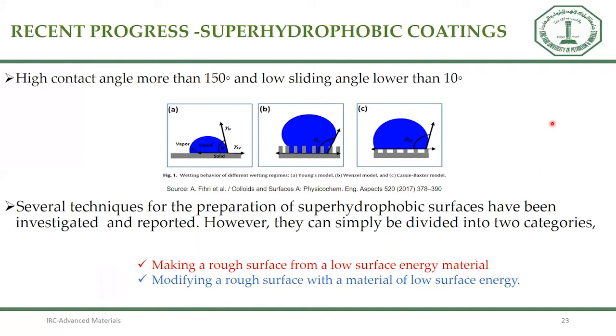From the morning, our colleague Dr. Saji explained well the importance of superhydrophobic coatings. So here I am going directly to how we can prepare the superhydrophobic surface on the epoxy coating: making a rough surface from a low surface energy material, and modifying this rough surface with materials of low surface energy.